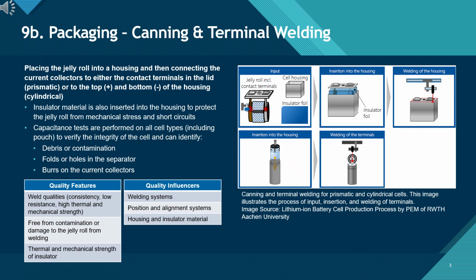Step 9B for packaging, canning and terminal welding. In this step, we place the finished jelly roll into a rigid housing, either prismatic or cylindrical, along with an insulating layer to prevent mechanical damage or electrical contact with the can. Once positioned, the housing is sealed, and the terminals are welded.